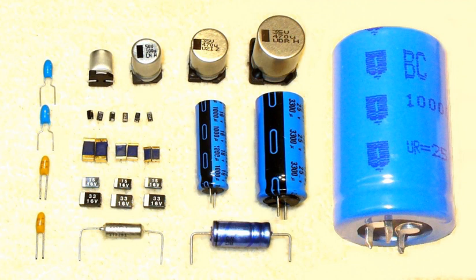For aluminum electrolytic capacitors with a rated voltage of up to 315 volts, the surge voltage is 1.15 times the rated voltage, and for capacitors with a rated voltage exceeding 315 volts, the surge voltage is 1.10 times the rated voltage. For tantalum electrolytic capacitors, the surge voltage can be 1.3 times the rated voltage, rounded off to the nearest volt. The surge voltage applied to tantalum capacitors may influence the capacitor's failure rate.